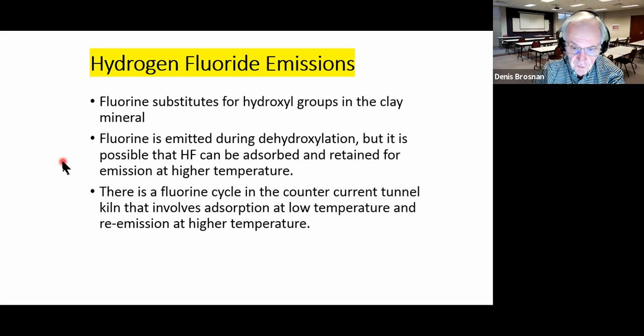Now, fluorine is released on heating in a tunnel kiln. It can condense on water molecules in the kiln exhaust as the draft goes toward the smokestack, and the heat that's present can release it at higher temperatures. So we get a continuous fluorine cycle in the cooling section of the kiln. Evaporation, condensation keeps happening. And whenever you have that kind of cycle in the dynamic process, occasionally the kiln is going to put out a spike of hydrogen fluoride. That has happened.